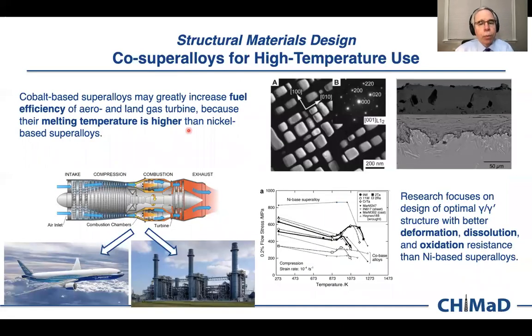We're looking at cobalt superalloys for high temperature use, and here the idea is to use a higher melting temperature of these cobalt superalloys to enhance the efficiency of turbines for either aircraft or land-based applications. And the focus here is on the precipitates, which are gamma prime precipitates, their dissolution and coarsening process, as well as the oxidation process on the surface, which is an extremely important part of the cobalt superalloy development process.